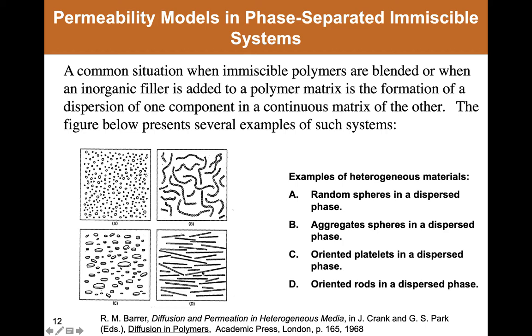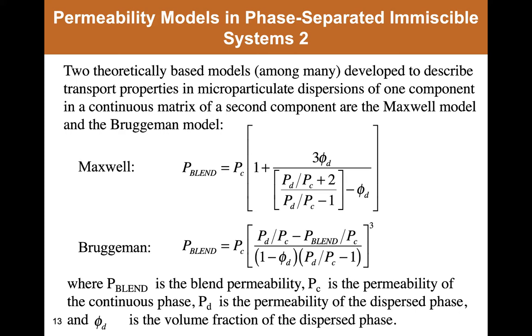And a couple of the well-known models of this type are the so-called Maxwell model and the Bruggeman model. The Maxwell model is, this is James Clerk Maxwell, the Maxwell from physics, who did a lot of work in modeling the electrical conductivity of heterogeneous systems. And in fact, the mass transfer analog of his electrical conductivity studies is shown here. And the Maxwell model is commonly used in the membrane literature to model, or at least as a first approximation, to model the permeation properties of, for example, a zeolite dispersed in a polymer.